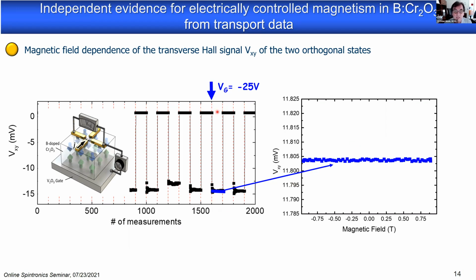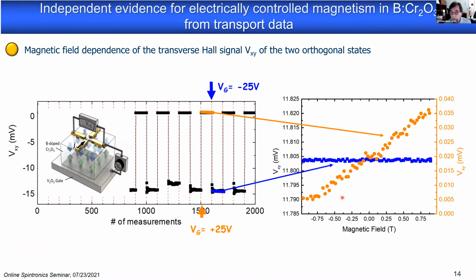Now we switch the system into that 0 type of voltage state, and we see suddenly a difference. We see a very significant field dependence. By the way, these scales are made in such a way that you can directly compare them. So it's not that one is artificially blown up with respect to the other. So here is a magnetic field dependence, here it is not.